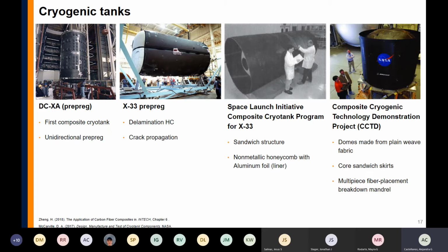And then they started the project with the X33. And again, one of the big problems that they found is delamination. And remember that delamination occurs because of the interlaminar region that is very susceptible to damage. So we're still having these problems. And also they found that there was a lot of propagation through the unidirectional prepreg. So learning from the X33, the Space Launch Initiative Composite Cryogenic Program decided to use a sandwich structure. And if you remember, the sandwich structure is made of two face sheets that are bonded to a thick core. And in this case, they used an aluminum liner to prevent any leak on the tank.